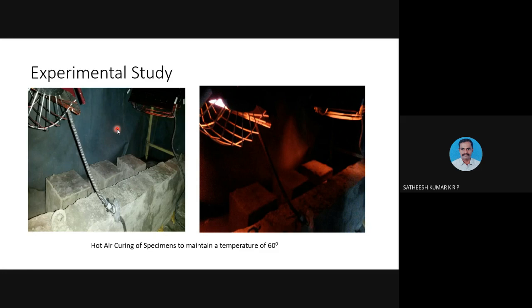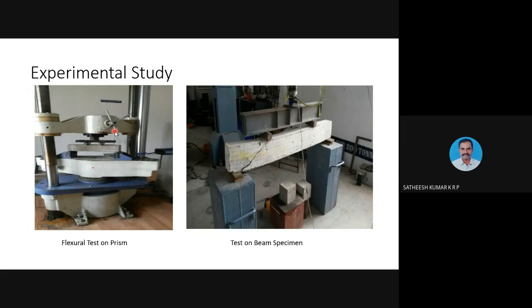We also had steam curing. For steam curing also, we were using a closed enclosure, but the facility is much larger than this. So we were directly using steam curing machines. And this is the experimental setup which we used for the flexure test on prisms. This is a universal testing machine in which we used the arrangement for the flexure test on prisms.